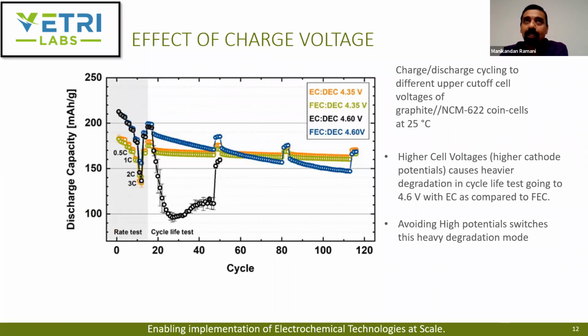I think I agree with that conclusion, that it is not associated with that, but it is probably a chemical stability between oxygen ethylene carbonate versus fluorinated ethylene carbonate. So for some reason, oxygen reaction with ethylene carbonate versus a fluorinated ethylene carbonate is more inert than an ethylene carbonate. That's kind of at least a hidden conclusion there, that fluorinated ethylene carbonate is more inert to oxygen, which kind of makes sense. Most of the fluorinated compounds are more inert than non-fluorinated compounds. But they don't really talk about it, so that's probably where we have to take a leap of faith on that one.